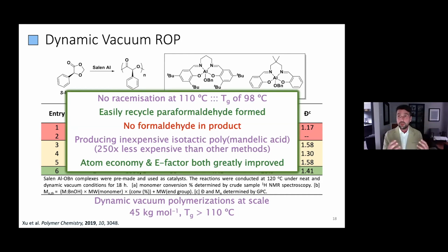When we do the polymerization, there were some people who were concerned about formaldehyde. Well, when I form that polymer, the paraformaldehyde exists as a sort of crust at the top layer of our reaction vessel. We can simply scrape it out, put it into a new monomer synthesis, and are ready to go. And it's interesting because you'd think there'd be a little bit of formaldehyde left in the product, but any formaldehyde that is left behind actually gets incorporated in this Tishchenko reaction to change our end groups. So we have no free formaldehyde in the product.